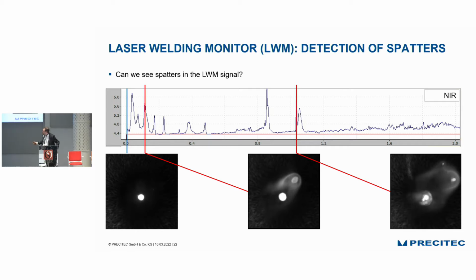For example, here, this is the keyhole, this is the spatter corresponding to this peak. This is the keyhole severely deteriorated after the spatter event corresponding to these peaks.